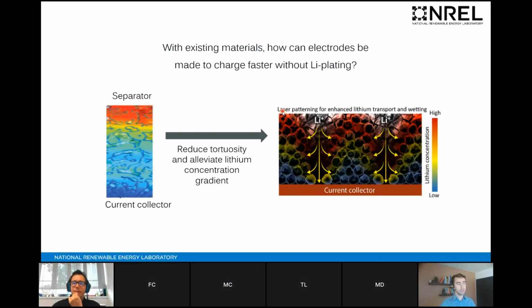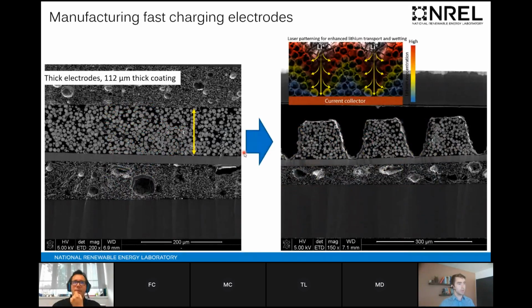And we do this by introducing highways, or low tortuosity channels, inside the electrode to facilitate lithium ions reaching deeper into the electrode at the earlier stages of the fast charging process. And this is a kind of taster of what's to come.